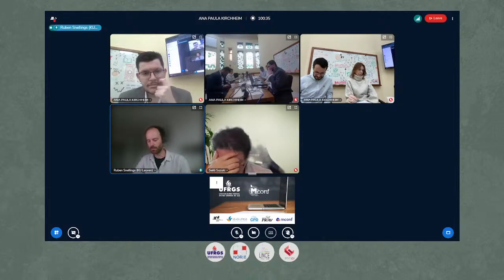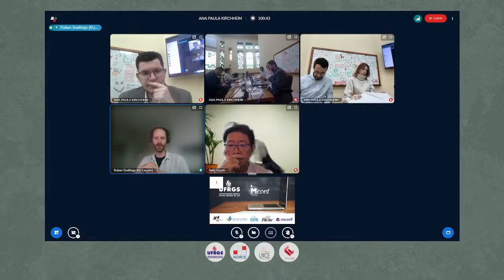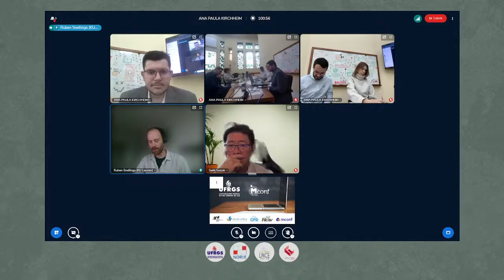Yes, and then, well, I think it also comes together with checking the mass balance, because yes, the sulfate sorption is very much also a result of doing such a mass balance and finding out that, say, sulfate is missing when we look into the amount of ettringite which is formed. And well, I think you make a very interesting contribution, noticing that alkalis impact the amount of sulfate you need in cements, and that this is related to the reaction rates of the C3A, of the C3S and so on, producing more CSH.